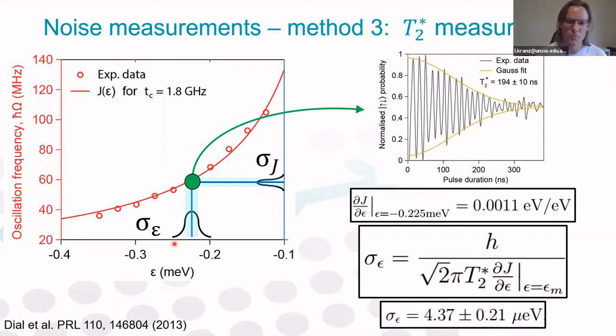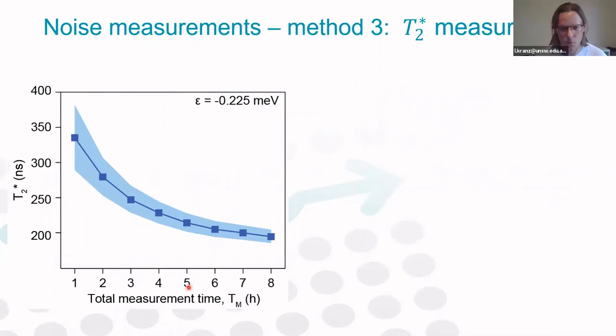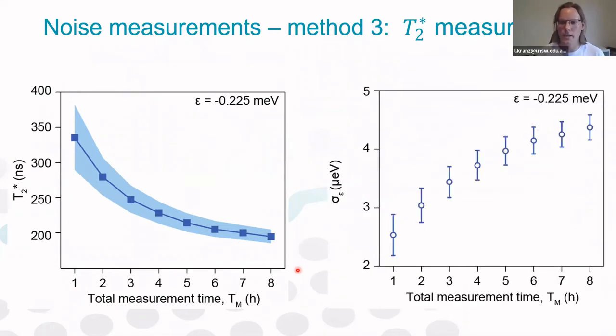So basically, what we did, we assumed this Gaussian distribution of detuning noise, which implies that the noise would be white. But as we know from the first part of my talk, the noise that governs the charge fluctuation has 1/f dependence. So to investigate this in more detail, we measure T2 star as a function of total measurement time, and we see a measurable decrease in T2 star over time. And for every data point, we can calculate the corresponding sigma epsilon, and we see that it's changing with the total measurement time. So for example, by reducing the total measurement time to 1 hour, we get a sigma epsilon of something like 2.5 micro eV.